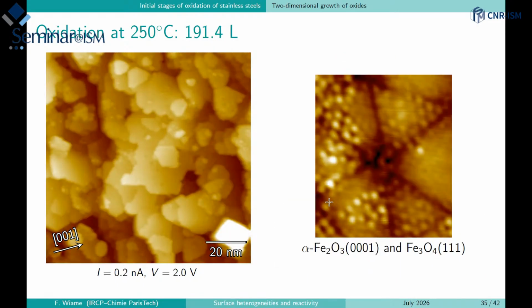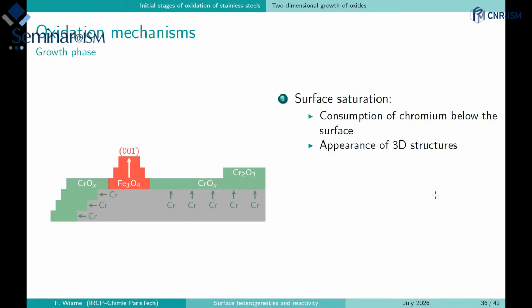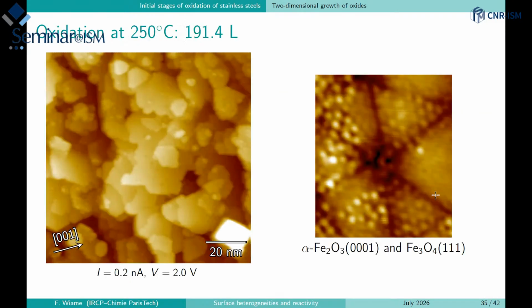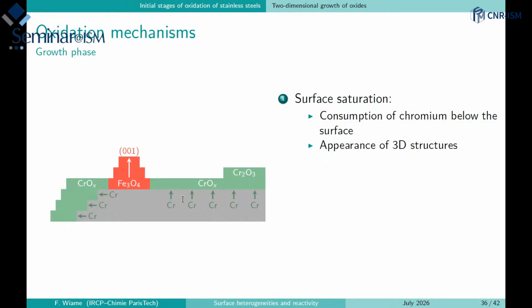So if we are continuing to about the saturation, we can see here that the surface is fully covered with the chromium oxide, but with some dots of iron oxide, and iron oxide which is forming on top of the surface. If we are looking at the structure of the surface, we can identify mainly iron oxide, the chromium oxide being below the iron oxide. So if we summarize, that means that we have initially this iron oxide that starts at the very beginning, that is growing fast, and also at